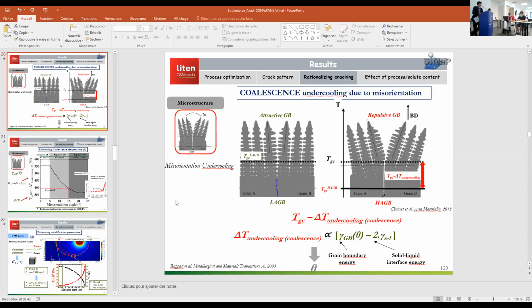Yes, the grain boundary energy is mainly a function of the angle, the misorientation, and maybe to a second order of the surface active element. But surface active elements definitely will impact things like viscosity as well. Viscosity will impact the solid liquid energy. It's like sulfur in steel. Like sodium, strontium. Of course, then you can restart a PhD work. I mean, you have all the periodic table to work on.